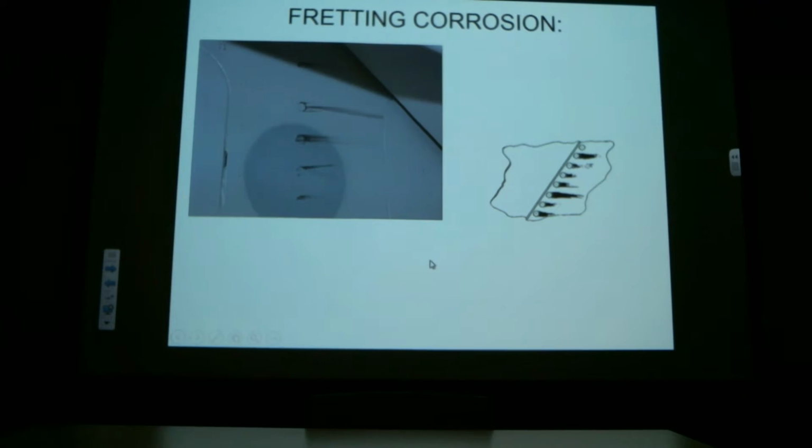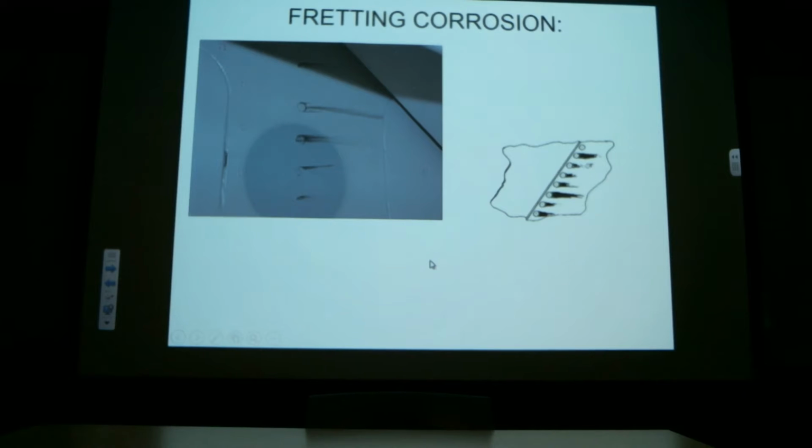This is caused a lot of times by very close fitting parts where the oxides of that rivet shank can't escape freely. So it acts kind of like an abrasive to cause further breakdown of the shank. These are called fretting or working rivets. And it's really a type of corrosion in a way because the aluminum is oxidizing and it's abrasive in nature.